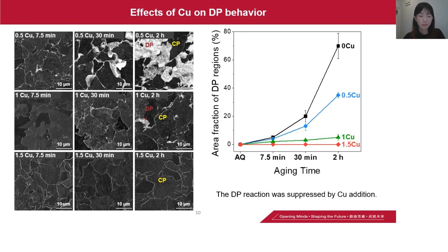From the SEM microstructure, it is observed that the area fraction of DP regions decreases with the increase of copper additions. Increasing the copper content to 1.5% results in a complete suppression of the DP reaction.